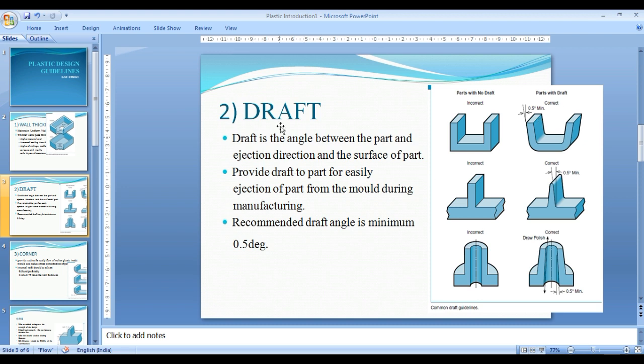Provide draft to the part for easy removal and ejection of the part from the mold during manufacturing. Recommended draft angle in plastic design is 0.5 to 3 degrees.